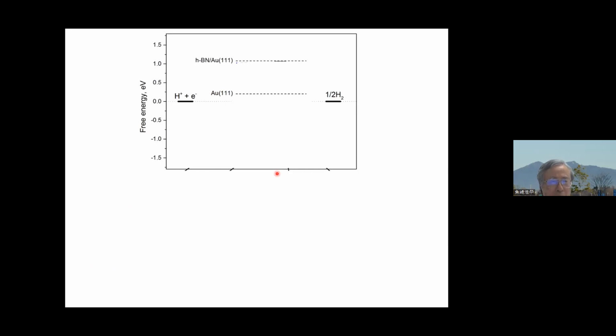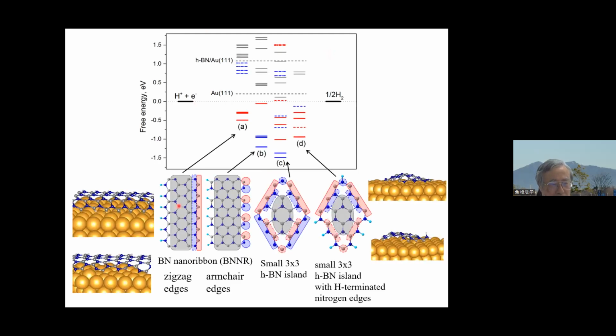If it is the monolayer boron nitride, it's very high. So it's not good. However, by using several types of small boron nitride nanoribbons, boron nitride islands, and so on and so forth, there's a very wide variety of adsorption states, and actually there are several sites which allow a very good intermediate state. So actually these are the edge atoms. So edge atoms play very important roles.